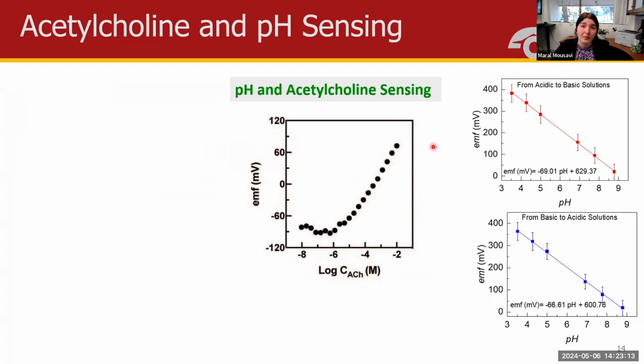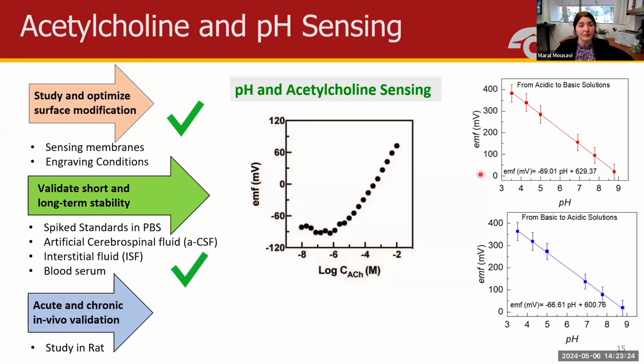And then we look at stability, measurement range, etc. And same for the pH sensor. We're looking at hysteresis, slope, and stability of the film over time. So far, we've optimized the engraving conditions, the deposition conditions, and the composition of our sensing membrane. We're right now in the middle of our aging studies and long-term performance studies, and then we'll shortly move to acute and chronic studies in the rats.